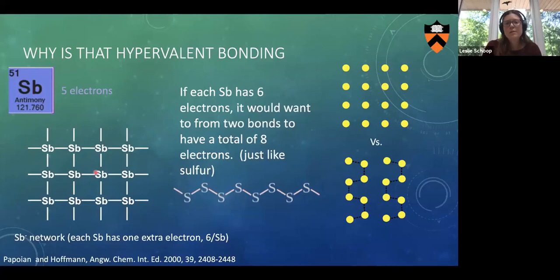And so basically what you learn from this is when you have a fully square net with this electron count, six electrons per net atom, it must be hypervalent or it needs to distort into forming zigzag chains. And this would be a Peierls distortion to have this preferred conformation. Okay, so we are again at the brink of a Peierls distortion, as we discussed in graphene or the hydrogen chain, in that here this band structure has too many electrons. If I were to localize these electrons into these bonds, then I would get a semiconductor.